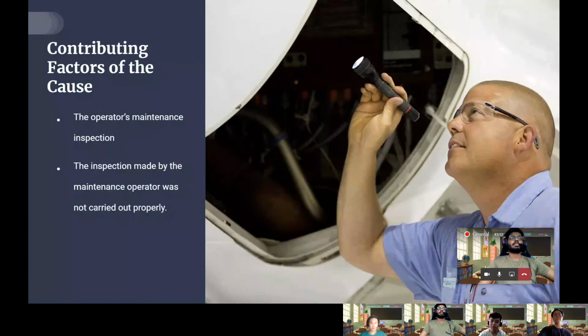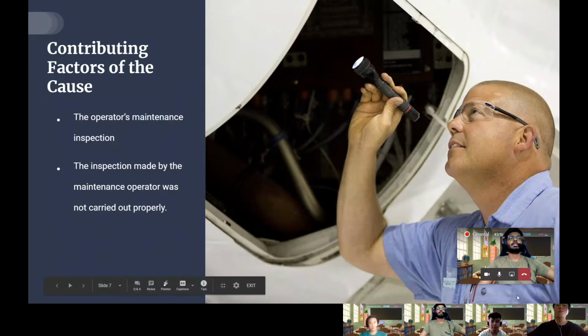Another contributing factor that led to the crash of China Airlines Flight 611 was improper operator maintenance inspection. After the China Airlines maintenance team had done their maintenance, the operator that was meant to inspect the maintenance done on Flight 611 did not detect the ineffective 1980 structure repair and the fatigue cracks that were developing under the repair doubler. If the operator had found out about the ineffective structure repair and the fatigue cracks under the repair doubler, the crash of China Airlines Flight 611 would not have occurred.